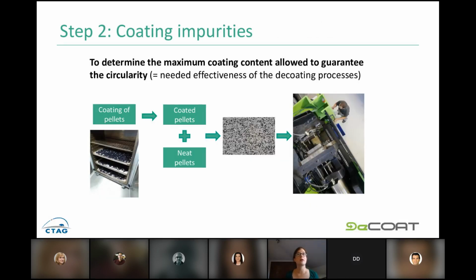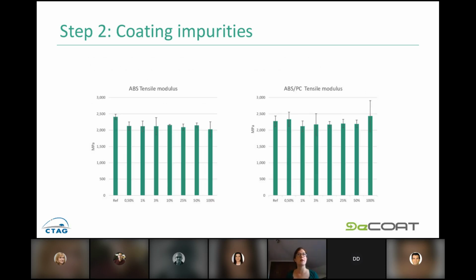Regarding the coating impurities, as I mentioned before, we added a controlled amount of coating in our testing campaign, and we see the results also with tensile modulus and impact strength. Regarding the tensile modulus, there is a slight effect on this property, with a variability of data that increases with the amount of impurities. But in the case of ABS-PC, it's quite stable. There is almost no variation in the tensile modulus. ABS is more sensitive in this sense.